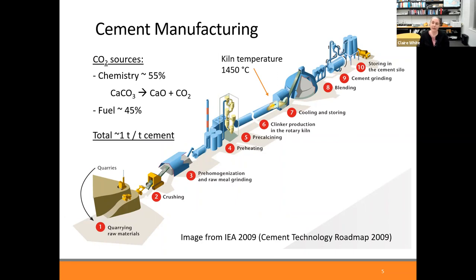Returning back to cement manufacturing, why are there CO2 emissions associated with the manufacturing of cement powder? Well, if you look at the industry, what happens is you dig raw materials out of the ground. Limestone is one, which is calcium carbonate, and also clays. And you heat them up in the kiln to really high temperatures, 1,450 degrees Celsius thereabouts. And so what happens at about 900 degrees Celsius is you get this decomposition of the limestone. And so it forms lime, calcium oxide, and then there's this CO2.